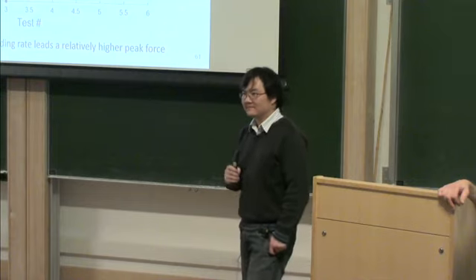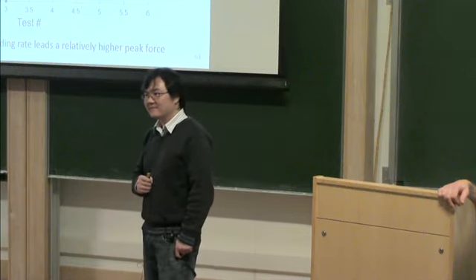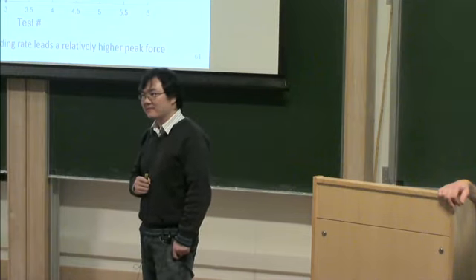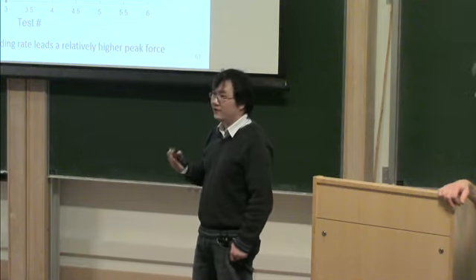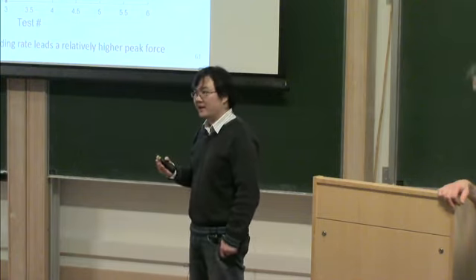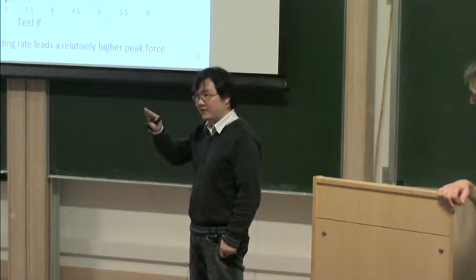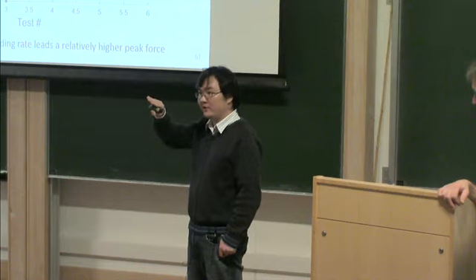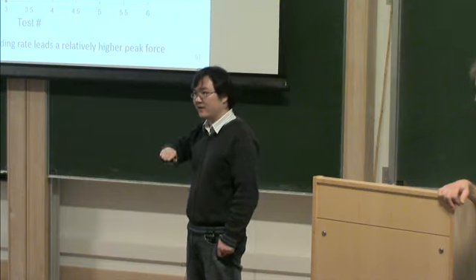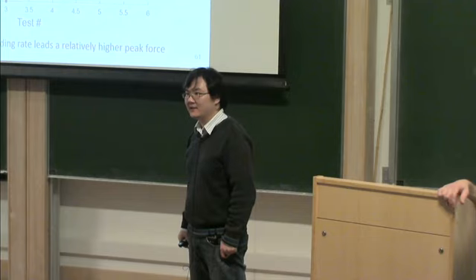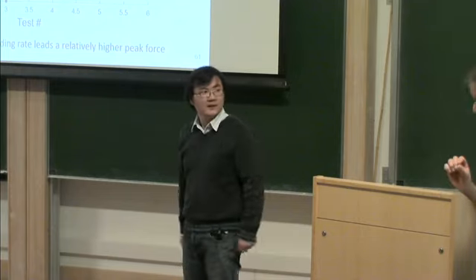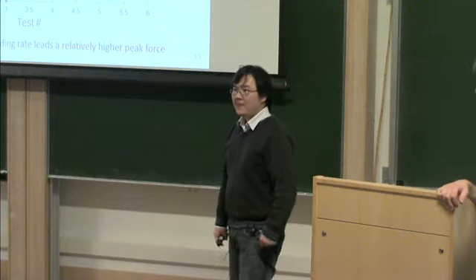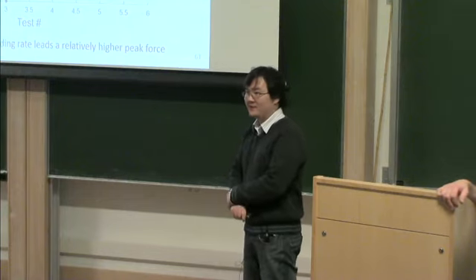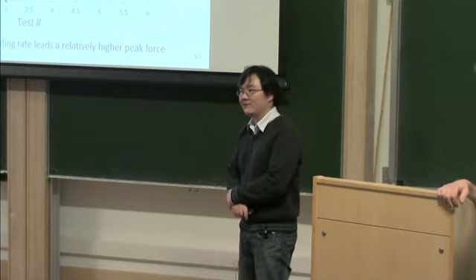Victor? Well, sort of related to that too, do you know if there is or is not any deformation ahead of the crack tip before your decrease of load? There is some deformation because we have like 4 gauges ahead of the crack tip. Before it fractures, we have this loading up, and we obviously see that those sensors are also being activated. There's opening. Yeah, there was like a displacement. Not much, but some. That's also the reason we want to use those data to back calculate this cohesive law.